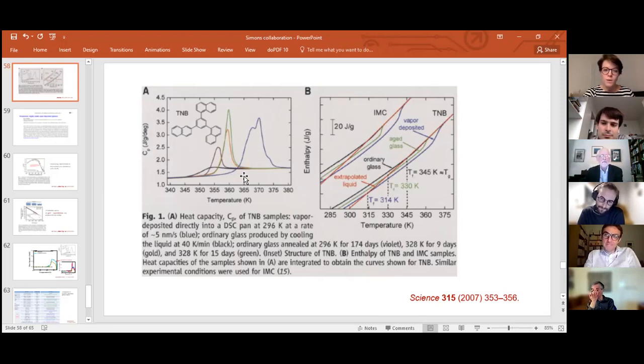And in your case, you don't see this shift, but you see a broadening, right? We just see that this peak is broader than it would be when you do it thermally, with a longer and longer anneal. The peak gets higher and higher, but it does not get broader. It stays the same width. Yes. Whereas with the mechanical process, it gets broader. But of course, that could just mean we have a rather imperfect process, which is giving us a very inhomogeneous sample. I don't know. Okay, maybe we can discuss another time, but thank you.